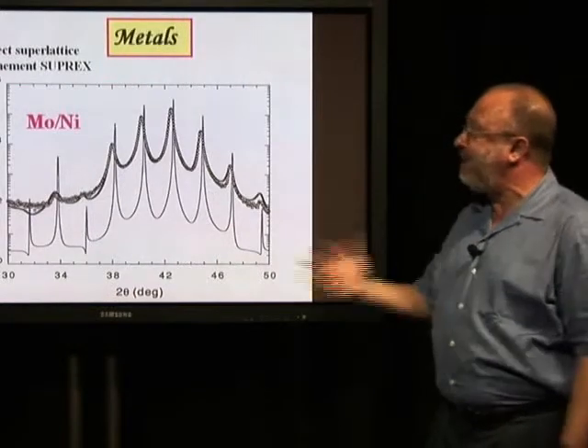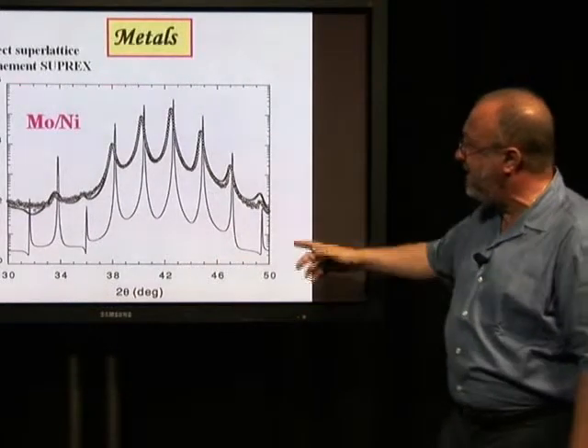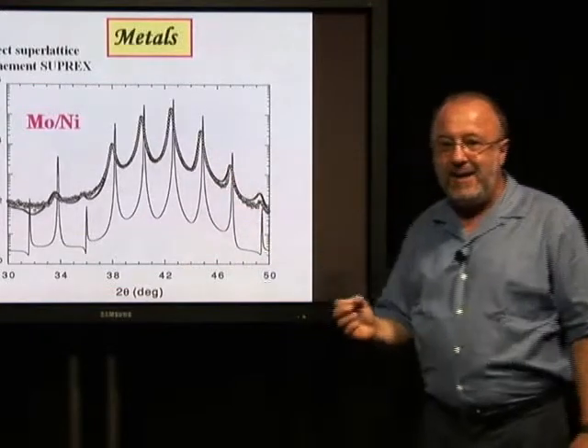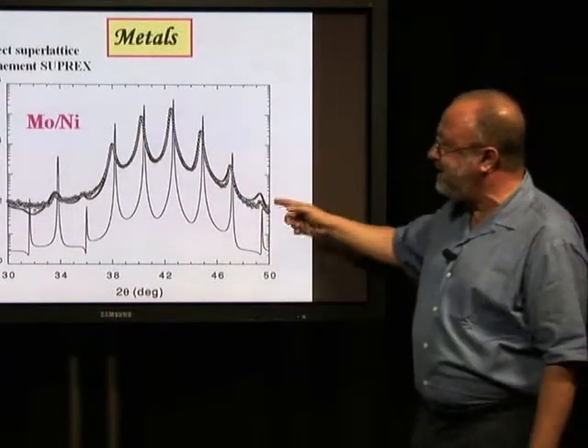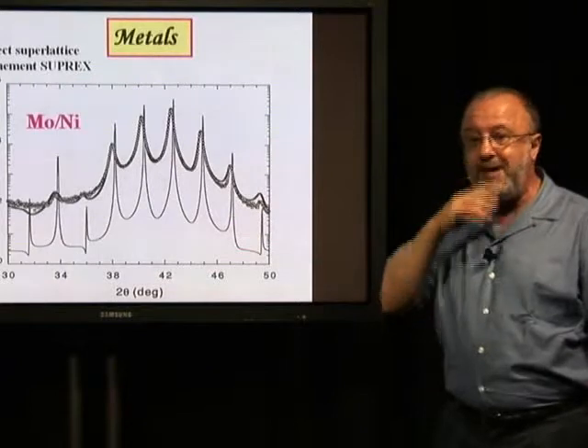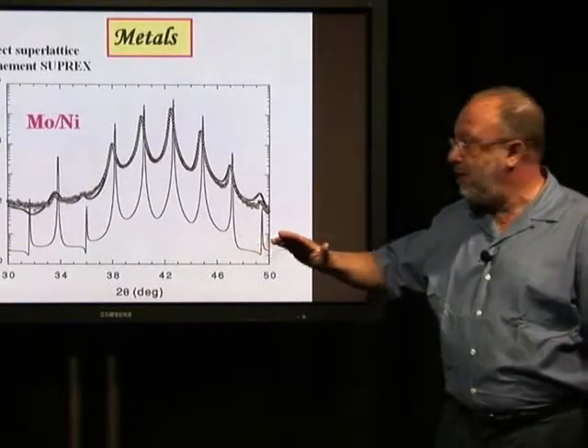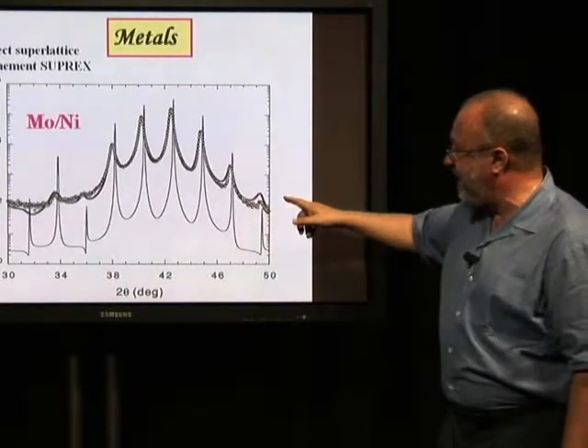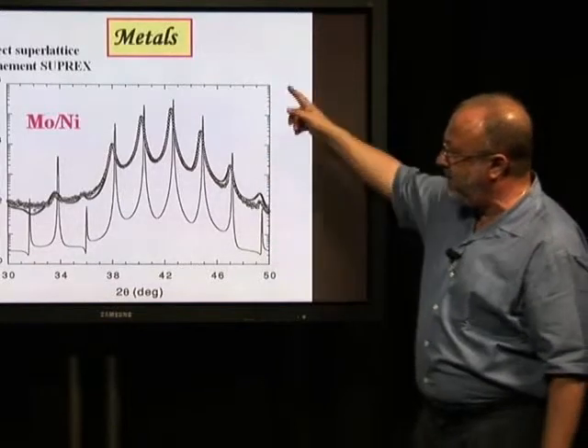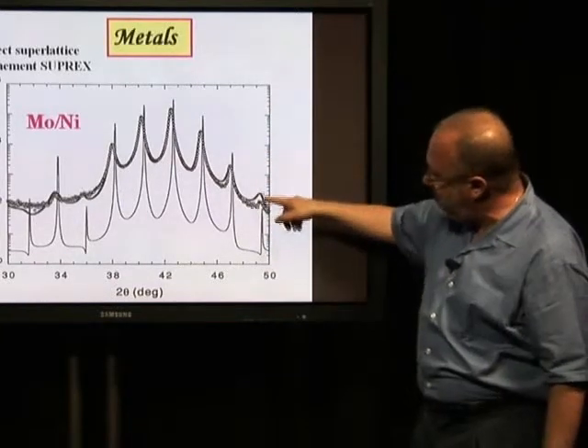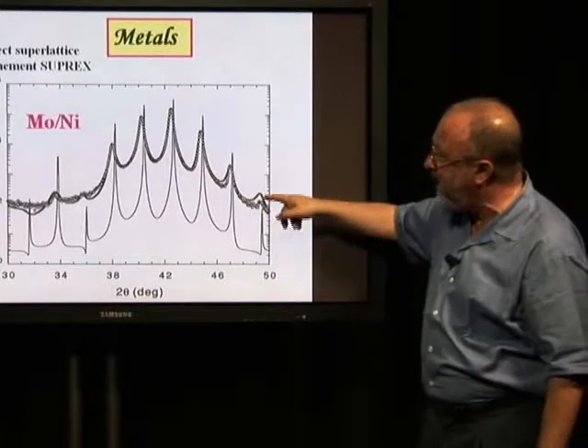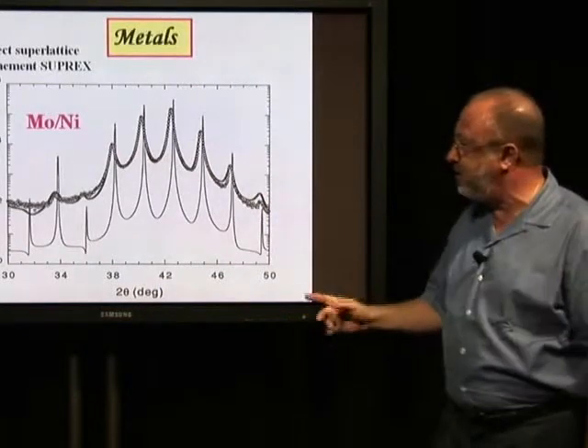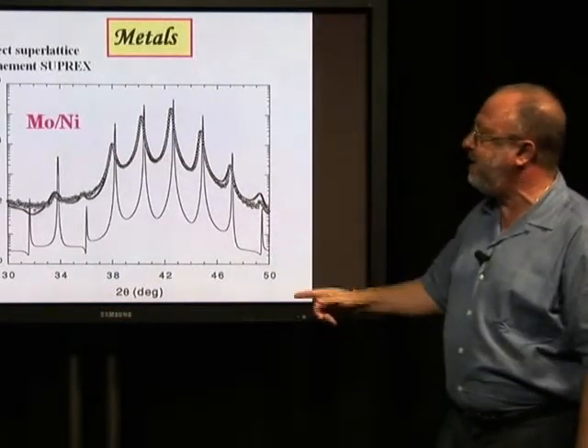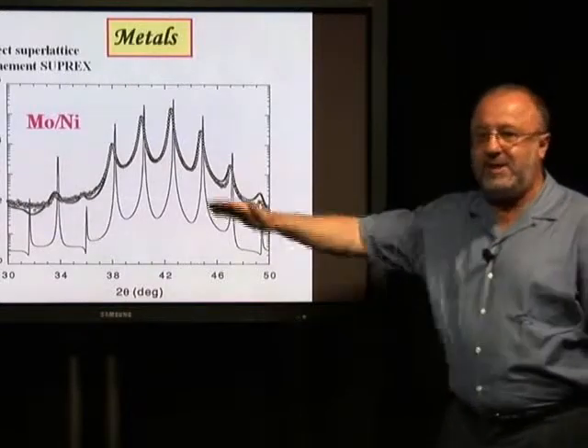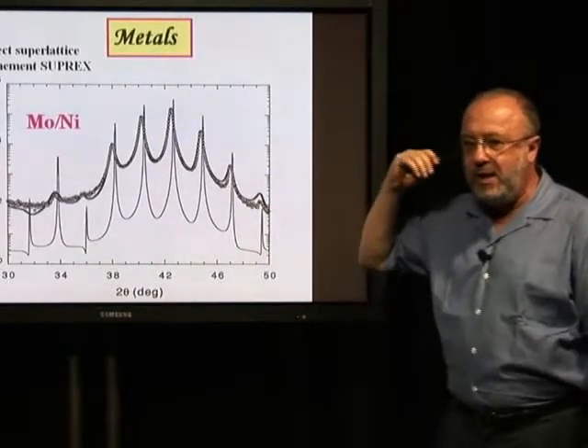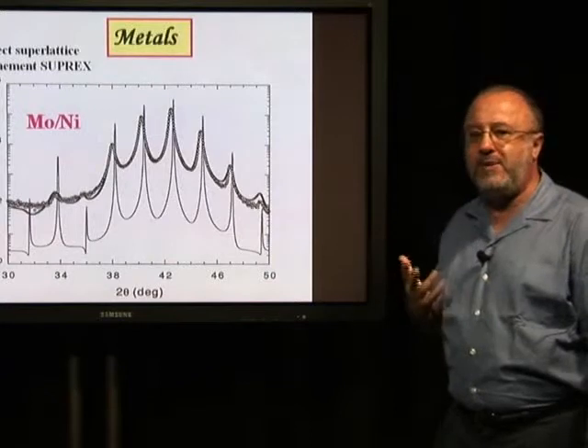What this refinement does for you, this SUPREX refinement, is basically fit the data. And how well the data fits tells you something about the characteristics of this interface. Notice here that this is on a logarithmic scale. So the small changes that you see here are really small. It's 1 part in 100. It's a very small change. So this is a very, very good fit. And this tells us something about the interdiffusion, about the roughness, about the expansions at the interface, many of the properties that we would like to know.